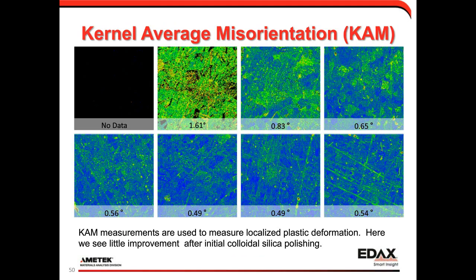However, in some cases, we may want to measure deformation. And so this is being measured here, plastic deformation, what we call our KAM, or kernel average misorientation measurement. This is a measurement that just looks at the small changes in orientation that are occurring. If we look at this at our 1 micron, our average KAM is 1.6 degrees, drops down to 0.83 with 0.3 micron, and then goes to 0.65 after 15 minutes, about 0.5 after half an hour, and then down to about half a degree after an hour or so, and sort of plateaus there a little bit. But it's the idea that a good final polish really starts to work at about 1 hour.